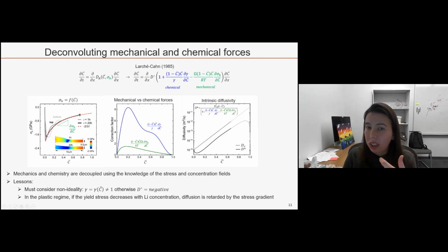If I consider this, given that I know the mechanical properties and the distribution of lithium, I can back calculate the property that I really care about, which is the intrinsic diffusivity. With this intrinsic diffusivity, I can model the stress effect and decouple it from the chemical driving force for diffusion. And I can even quantify which one is higher. In this case, the chemical driving force is much higher than the mechanical driving force. But the mechanical driving force is still significant.